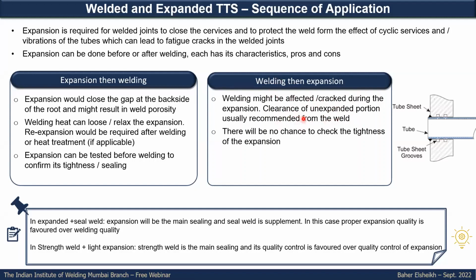That's why in the standards there is a recommendation to maintain a gap between the expanded part of the tube and the weld. You should leave some gap or clearance, not expanded, to avoid impacting the weld. And there will be no chance to do a tightness check for the expansion because the welding will already do the sealing. So after doing the expansion later, you don't have any standalone inspection technique or leak test to confirm that your expansion was applied correctly.